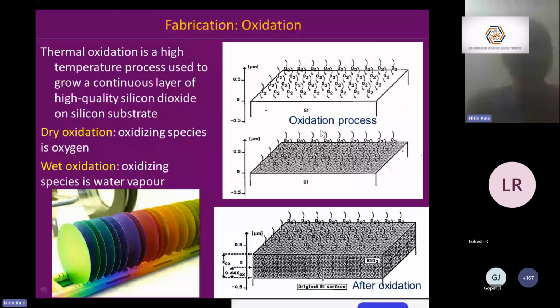Okay, silicon to silicon dioxide oxidation. It happens in furnaces at reasonably high temperatures. It is called a growth process because silicon is consumed. The substrate, which is the silicon wafer, is also consumed. It is done in the presence of oxygen, which is the oxidizing species. Sometimes it is done in the presence of hydrogen as well, because if you want a wet oxide, water vapor is the source for oxidizing. Silicon dioxide forms an extremely brilliant insulator. A superb insulator.